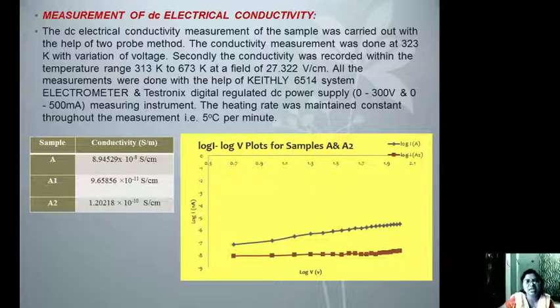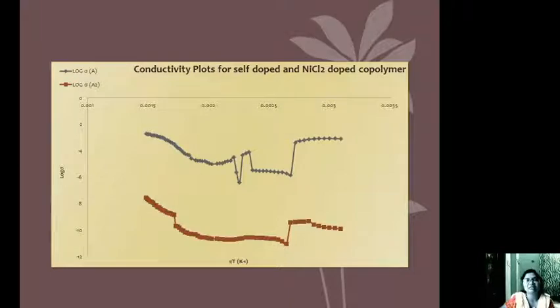From the conductivity measurement, it is observed that the conductivity of the prepared copolymer has been reduced to a greater extent. Further, when the temperature was varied, we observed that from 40 degrees to 110 degrees the sample exhibits linear behavior, but at a sudden transition temperature the sample drops from the metallic to the semiconductor state. This transition is very prominent in the self-doped and the doped copolymer. The undoped copolymer also exhibits similar behavior, but the conductivity value is very low, hence we have not reported it in this paper.